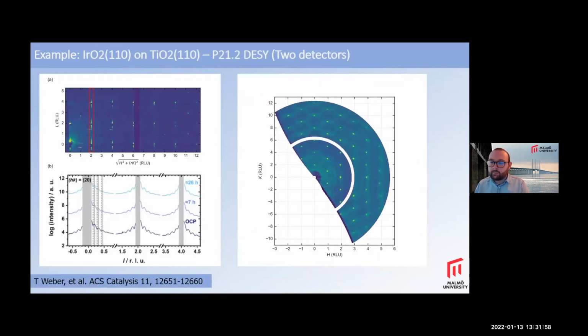Here's another recent example which we published where we actually used two detectors, so we could go further out into reciprocal space. So this was iridium dioxide on titanium dioxide. And in this case, we were looking at the stability. So actually not very much was changing, which was good.